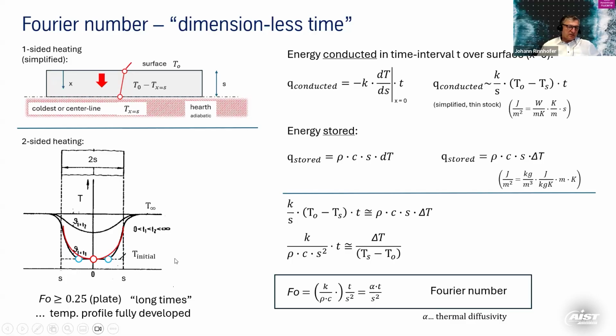And that is useful because, for example, for a plate, you can say everything with Fourier more than 0.25 means that you have a completely developed temperature profile. So even the center of the slab is already affected by the energy which you are conducting through the slab by heat transfer, so to say. Everything with Fourier less than 0.25 will mean you have some skin effect still. So the center of the slab is not affected by the temperature at all at the beginning of a heating process, for example, or if you have a very thick stock. So this tells us a lot, this Fourier number.